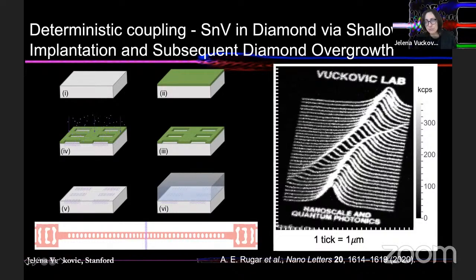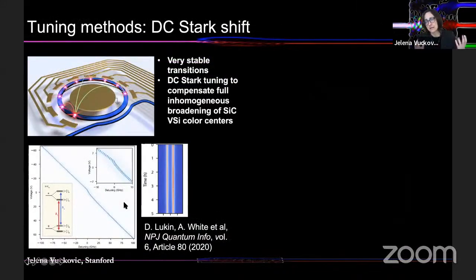But then for spectral inhomogeneities, we developed a few different techniques that could be used to overcome these residual spectral inhomogeneities. And most recently, actually, we focused on Stark shifting in both silicon carbide and diamond. In silicon carbide, we can just use DC Stark shift to tune the color center transition across the whole spectrum of inhomogeneous broadening. So you basically just put electrodes and tune the transition wherever you like. And in the process, you don't really degrade stability and properties of the color center.